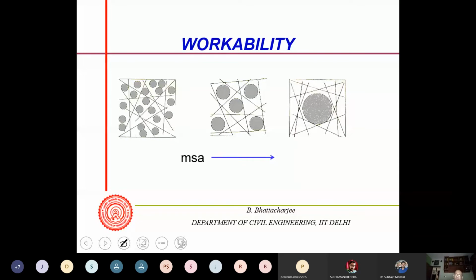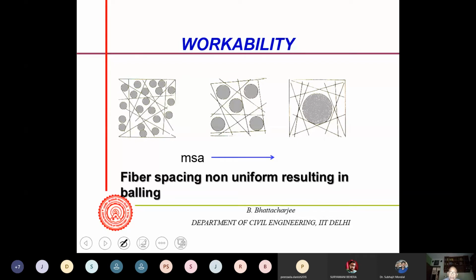Good fiber. So actually for high performance concrete, this becomes very good, because there we use around 50% paste to control what is called differential shrinkage. Bulk shrinkage is allowed, precast elements, but differential shrinkage we control. So their fiber gives you good ductility, and it's being used actually. So fiber spacing is non-uniform if you have larger aggregate, resulting in what is called balling action. These fibers will form balls, and there will be voids inside. They bring down the properties and compaction becomes difficult.